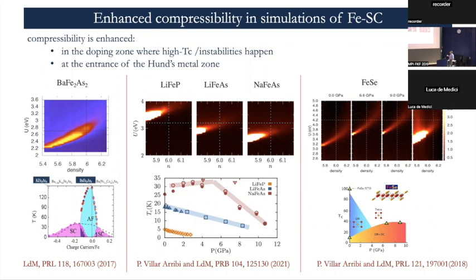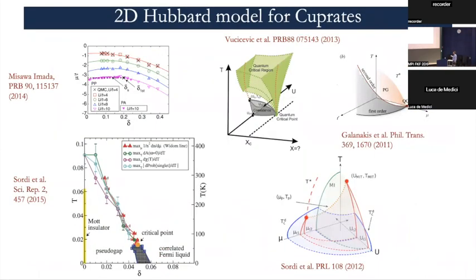This can be put in positive correlation with the trends in Tc that are found in different families of iron-based superconductors. Here, monolayer iron selenium, or the 11 family. So our message is that this enhanced compressibility might actually be a booster of whatever mechanism of superconductivity is happening in this area, because we always found the high-Tc compounds to be on top of this enhanced compressibility zone.